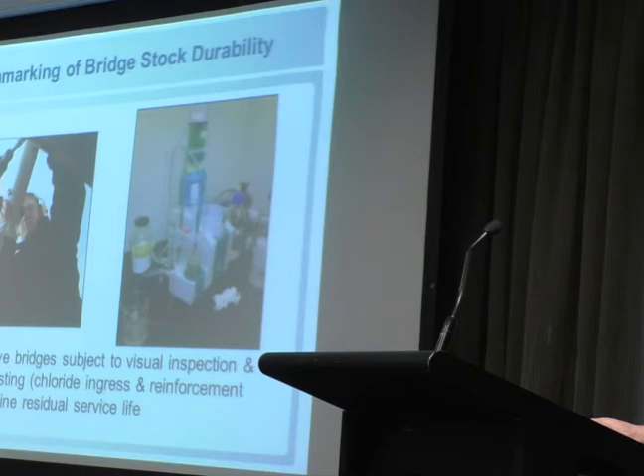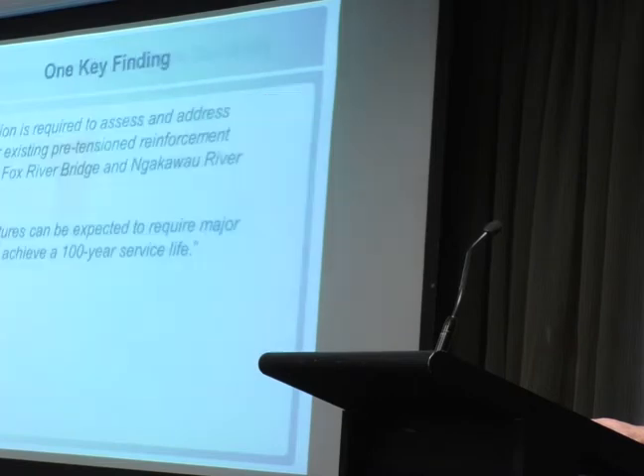So he went out and sampled 30 representative bridges, measuring chloride profiles and carbonation and cover and some of the other tests you've heard about. And one of his conclusions when he reported back to the New Zealand Transport Agency was that urgent action was required to ensure that two of their bridges did not suffer from premature reinforcement corrosion failure.